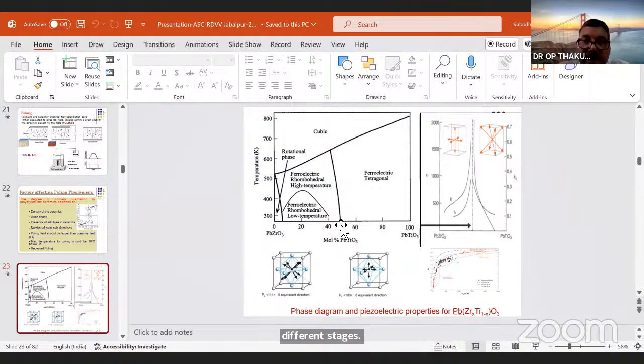It's just like in this boundary, if you choose the composition such that it falls in this region, that means the composition has the coexistence of both crystal structures, tetragonal as well as rhombohedral. So overall, the total directions for the orientation of dipoles is 6 plus 8, meaning 14 directions. If you get more directions, then you can easily align the dipoles in a particular direction. It's just like climbing stairs: if the gap between two stairs is very large, you will be tired, but if there is a small step, it's easy to climb. A similar phenomenon is there in the material also.